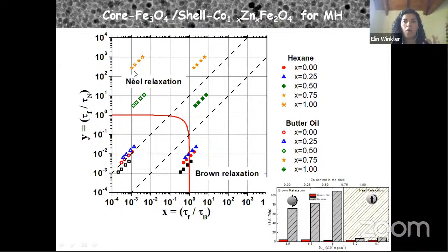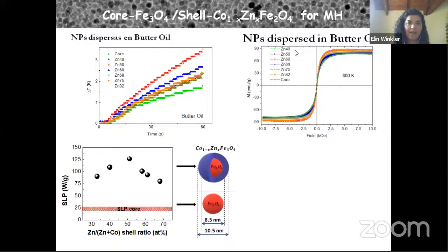If we want our nanoparticles to produce heating of the medium by the Neel relaxation, we have to make a fine tuning of the composition around this red line. And we did that. We started to fabricate a sample here, a sample here, and here, until we reached the maximum. Systematically fabricating around this red line, we obtained a maximum in the specific power absorption. And the active mechanism in this case is the Neel relaxation.